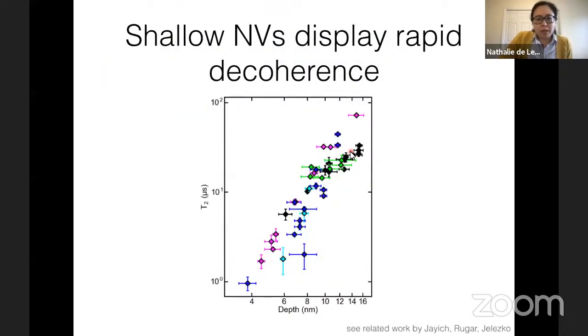And one of the ways that we know this is if you just look at individual NV centers and map out their coherence time as a function of depth away from the surface, we see this really terrible scaling. Again, deep in the bulk of diamond, your T1 at room temperature is something like 10 milliseconds. When you get within tens of nanometers of the surface, you start to see something that looks a lot like power law scaling. And by the time you're within a few nanometers of the surface, you see more like hundreds of nanoseconds of coherence.